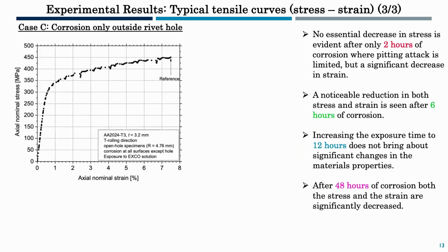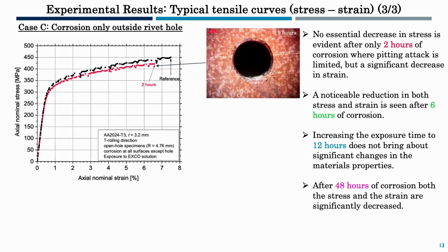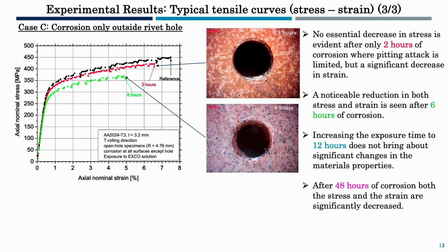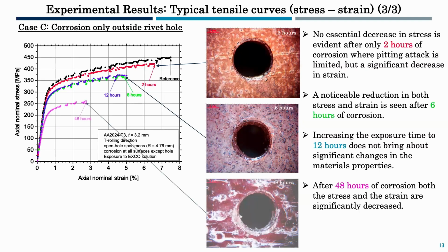Regarding the results for case C, where only the layers outside of the rivet hole were corroded, no essential decrease in stress is evident for 2 hours corrosion exposure time, where pitting attack is limited, but an essential decrease in strain can be noticed. A noticeable reduction in both stress and strain is seen for 6 hours, while increasing the exposure time to 12 hours, there's no significant decrease, neither in stress nor strain, but after 48 hours of corrosion, due to extensive exfoliation, both stress and strain are significantly decreased.